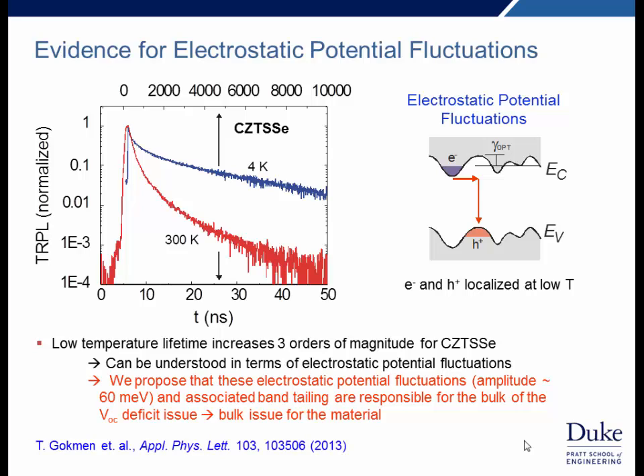Namely, if we lower temperature sufficiently, photoexcited electrons and holes will get localized into pockets which are physically separated, therefore reducing the opportunity for wave function overlap and likewise the opportunity for recombination. And so we propose that these electrostatic potential fluctuations and associated band tailing are responsible for the bulk of the VOC deficit issue in this material.